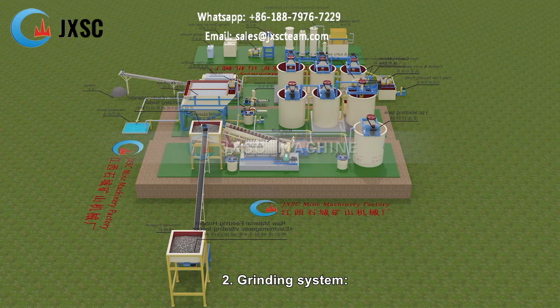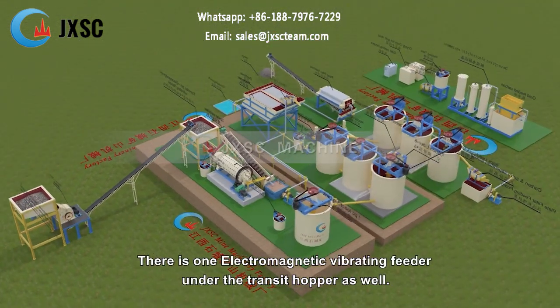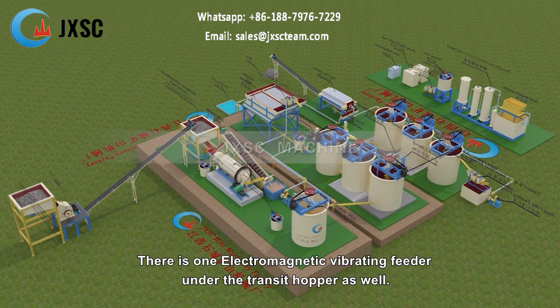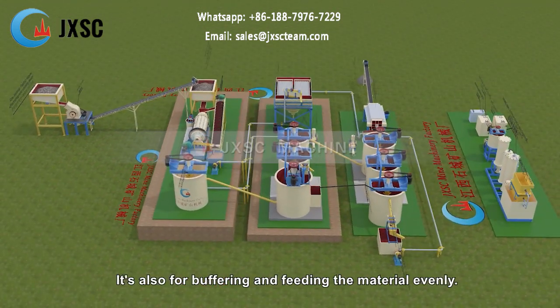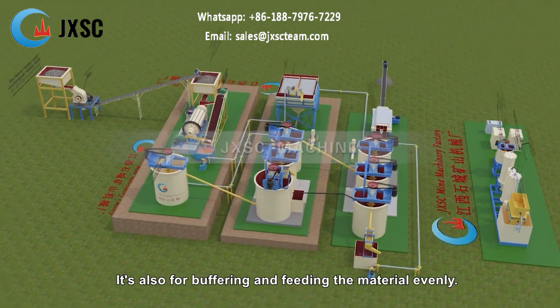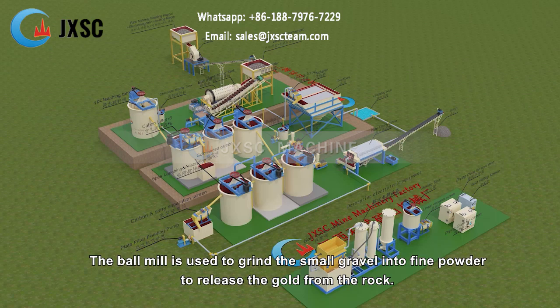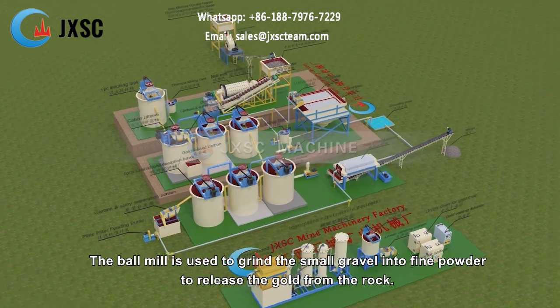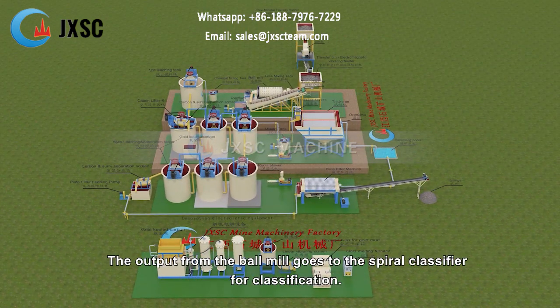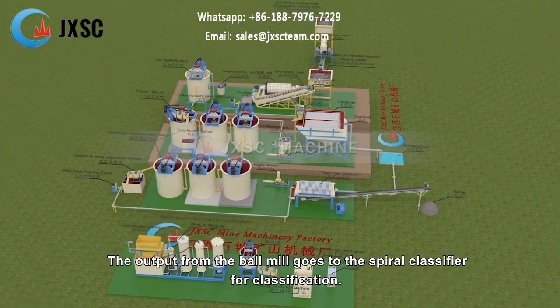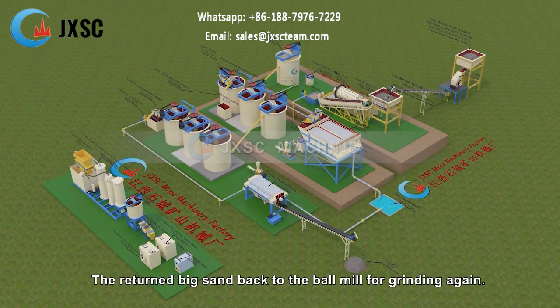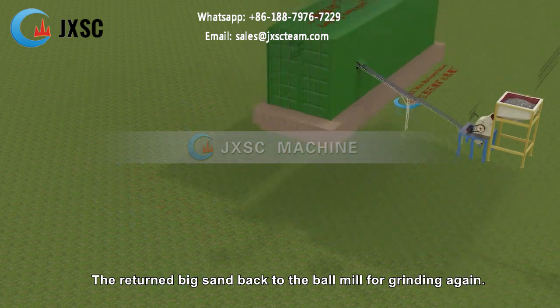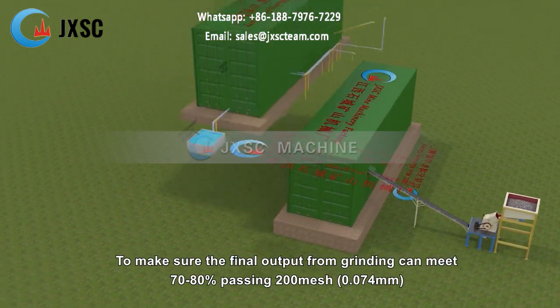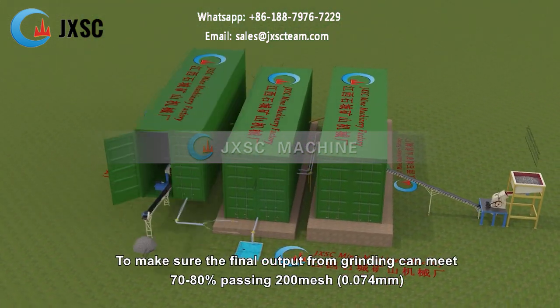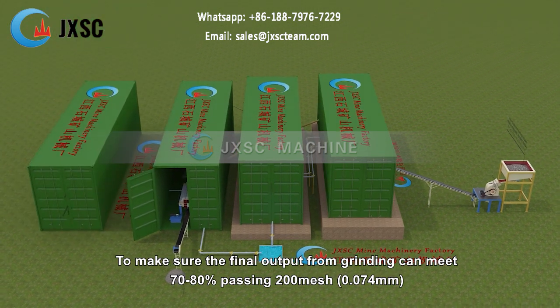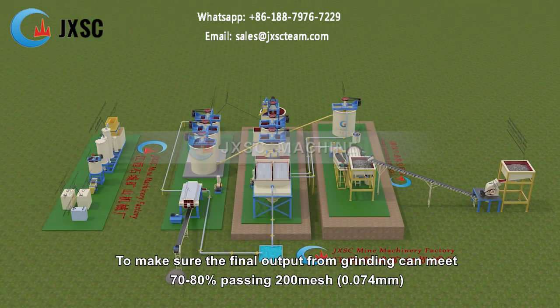2. Grinding system. There is one electromagnetic vibrating feeder under the transit hopper as well. It's also for buffering and feeding the material evenly. The ball mill is used to grind the small gravel into fine powder to release the gold from the rock. The output from the ball mill goes to the spiral classifier for classification. The returned big sand goes back to the ball mill for grinding again, to make sure the final output from grinding can meet 70 to 80% passing 200 mesh, 0.074 millimeters.